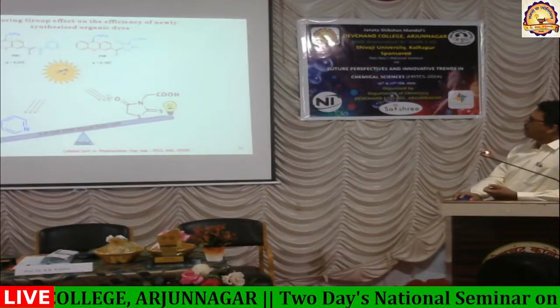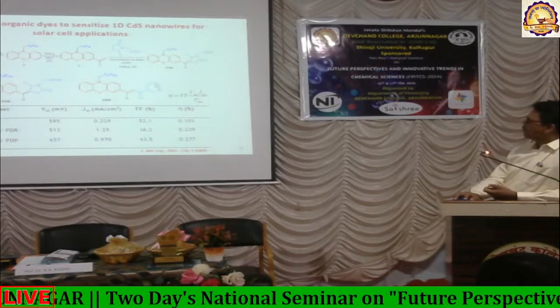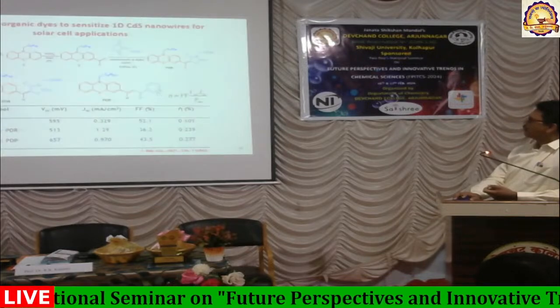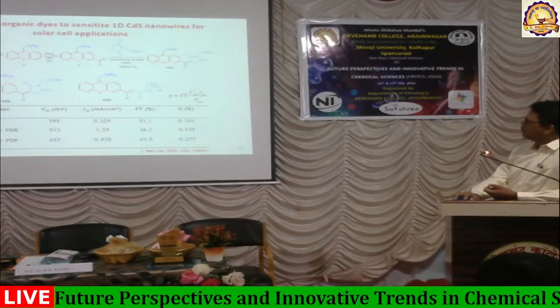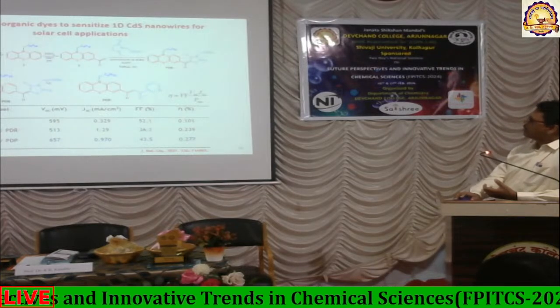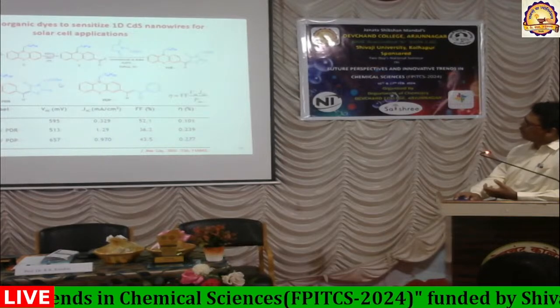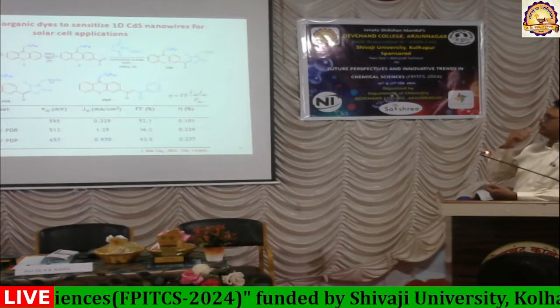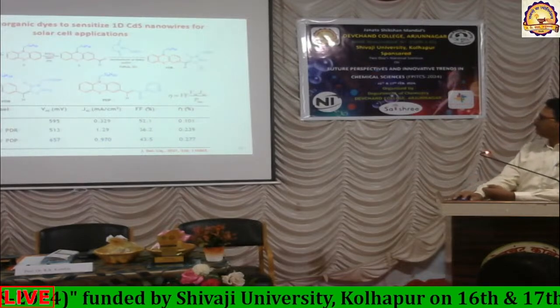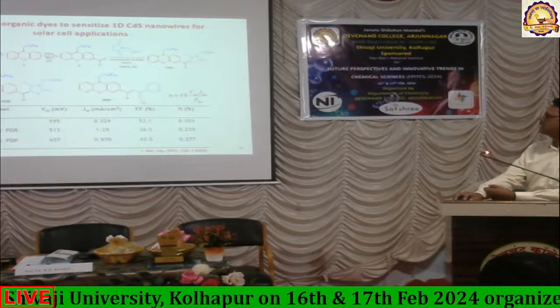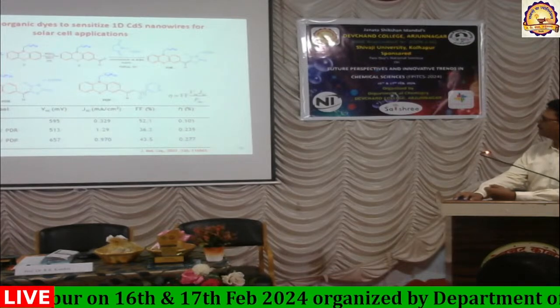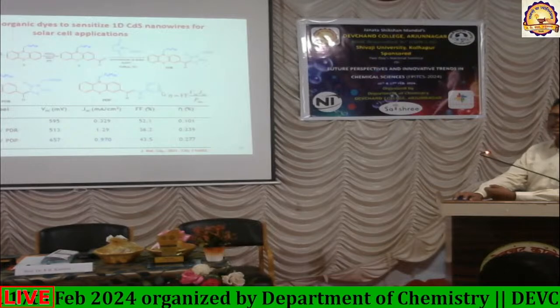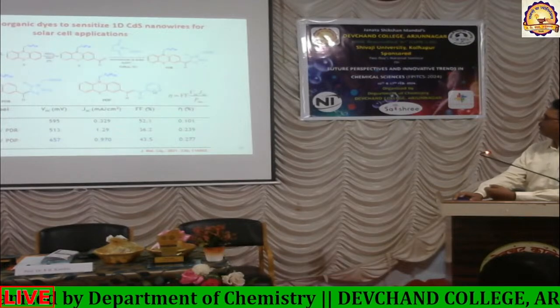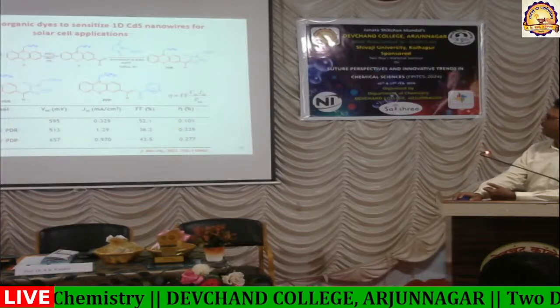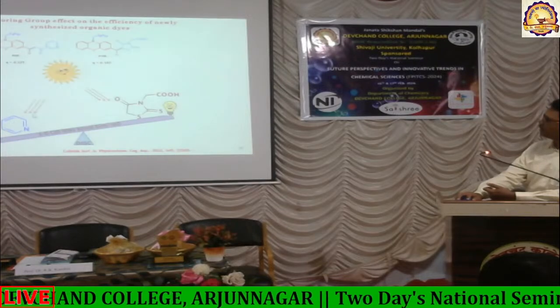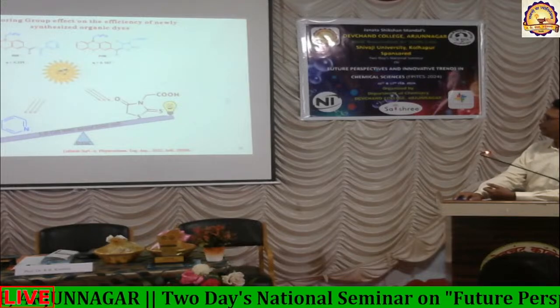So when we compare the rhodamine and this pyridine, a few papers showed that heterocycles, like the 6-membered heterocycle pyridine, can also work. What is the requirement for a linker? There must be a COOH which will link on the semiconductor. Here we introduced a linker without any such electron withdrawing group, but pyridine itself acts as electron withdrawing. Through its lone pair of electrons, it links itself on the semiconductor. We tried this for the first time, and we got more efficiency with the pyridine than with the already reported rhodamine 3 acetic acid.